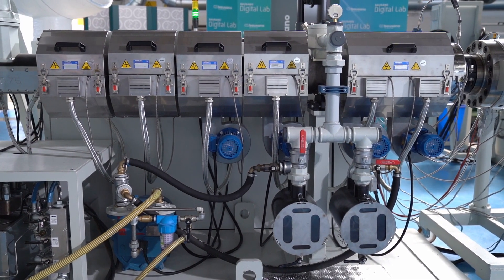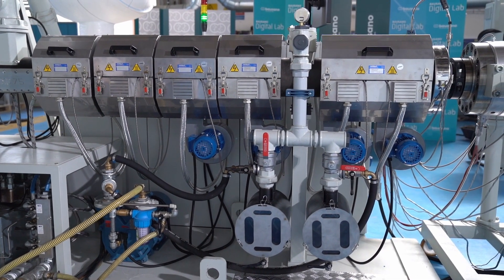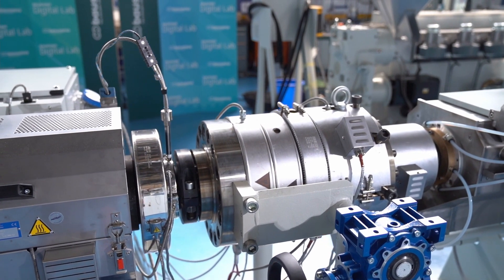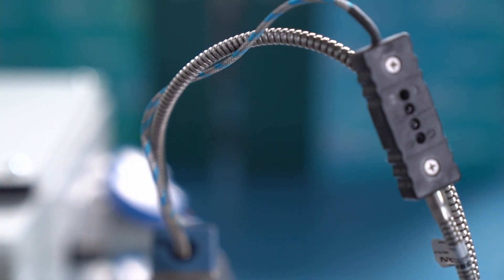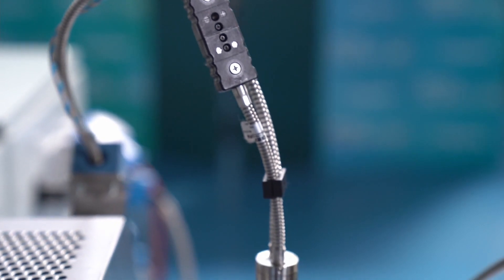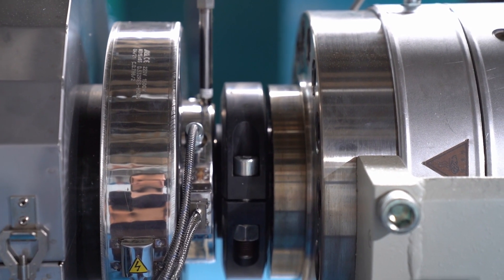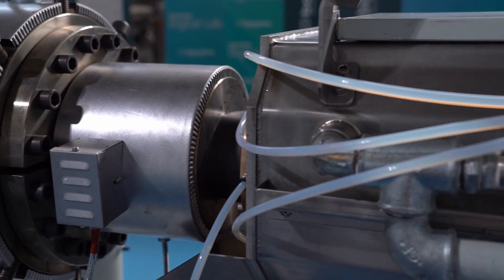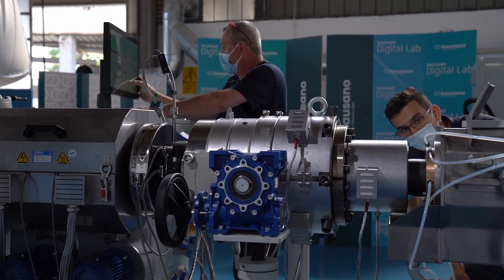The inside of the screws is drilled to allow the circulation of silicone oil. The circulation of the cooling oil is regulated by means of a thermoconditioning control unit, and the oil temperature can also be set from the extruder control panel. A degassing system is installed on the barrel; the venting is controlled by a liquid ring pump installed on the base of the extruder. The degassing system is equipped with a double filter that can be easily inspected during operations. Our extruder is also equipped with a pressure transducer to check the extrusion pressure. The probe enters a hole in the collector and measures the material pressure at the inner wall, with the value displayed on the control panel. At the same time, the probe also measures the melt temperature. And here we have the die head — the one my colleague Giorgio already showed you. The head installed in this line covers a range from diameter 63 to 110 mm.